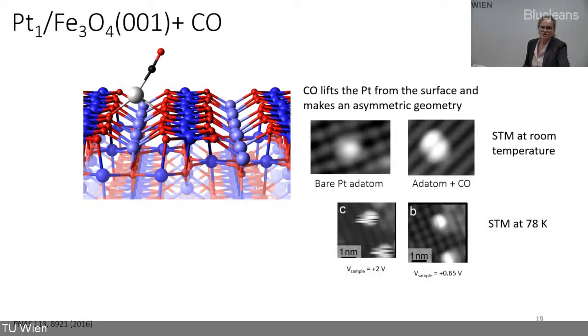Well, we can just cool down. If we cool down and take an STM image at low temperature, we freeze out this motion. And if we increase the bias voltage in our STM a little bit, you can see this streaky part - that means we started the wagging motion again, initiated by our STM tip.